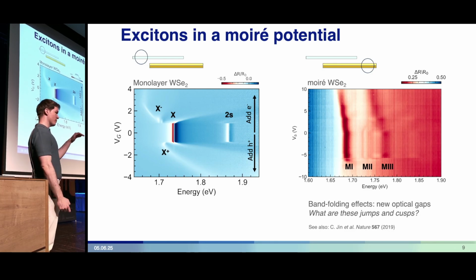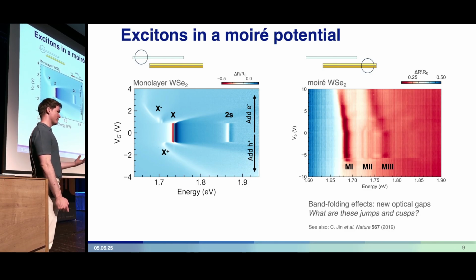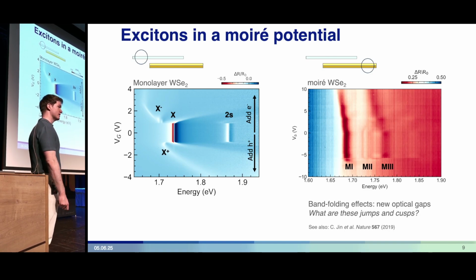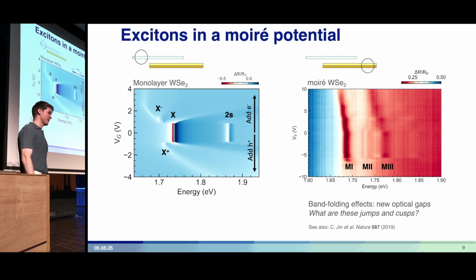This comes from reduced screening. And then the energy jump is associated with a change in the effective mass as you fill to the next band. So it's a renormalization effect, and that only happens because of the hybridization, that you detect with the exciton in the complementary layer.